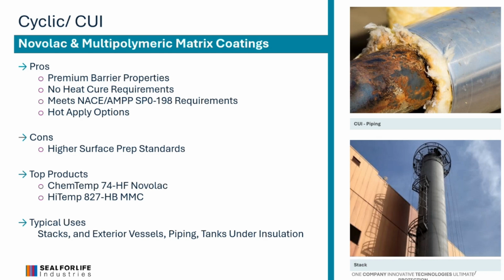Pros here, we have Novolac epoxies and multi-polymeric matrix coatings. These are premium barrier products. There's no heat cure requirements, so neither one needs to be heat cured. They meet SP0198 requirements, hot application options, higher surface prep standards are required for this, obviously with the temperatures that, once again, we can do CUI up to 1,000 degrees Fahrenheit. That substrate is going to start moving back and forth quite regularly if it's cyclic, and you will need to do better surface prep standards where you're getting to a near white or a white metal blast.